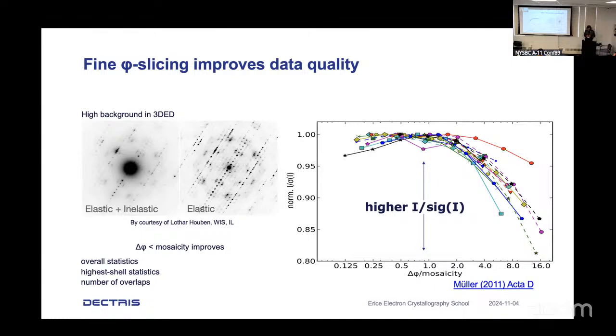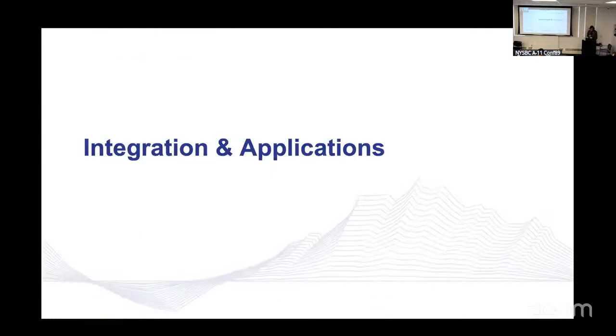This is data from Lothar Houben at the Weizmann Institute, which gives you significantly less background when you work with protein samples. Or what you can do, because the readout is noise-free, you can do fine phi slicing. This was shown for protein some time ago with Pilatus: you should take a phi range of about half of the mosaicity of your crystal. And if you don't know the mosaicity, you start with, say, 0.1 degree per frame.